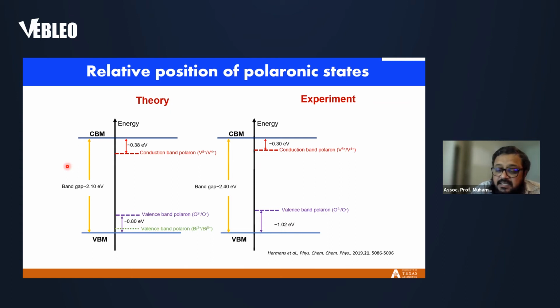Another question that needs to be asked is, what is the practical consequence of forming this polaronic state within the band gap? One of the consequences can be the reduction in photovoltage. That means if polarons didn't form, the photovoltage could have a higher bound of the fundamental gap. But now, because of the formation of this state within the gap, an overall reduction in photovoltage takes place. And that has been verified by the experiment from our collaborator at Darmstadt in Germany.